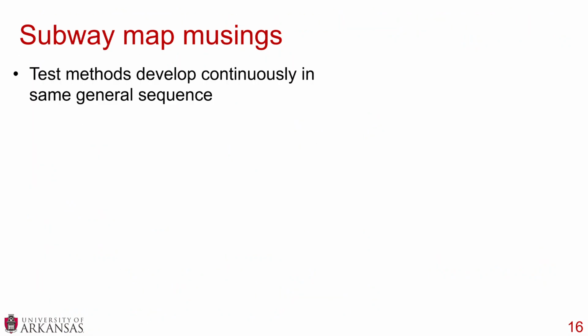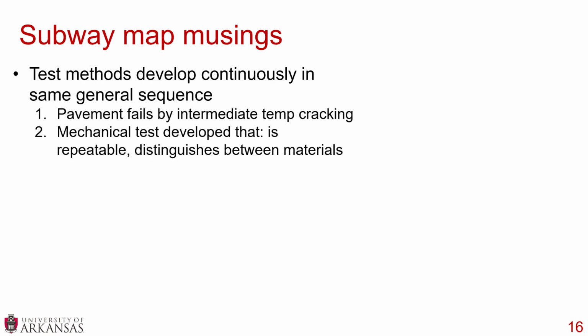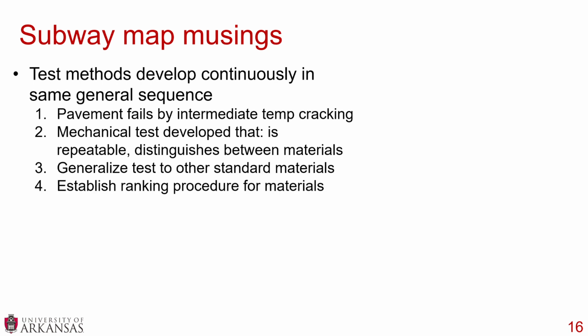So, what are some of our musings? So, all of these test methods were developed in the same general sequence. Someone notices a pavement is failing by intermediate temperature cracking. They develop a mechanical test that is repeatable and it distinguishes between the materials. They generalize that test to other standard materials and they establish a ranking procedure for materials. We feel that this is a specific sequence that every test method should go through in order to establish credibility.